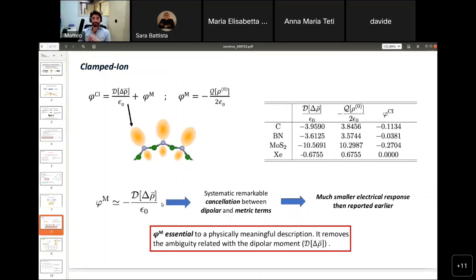We find that the Clamped-ion response, applying the prescription described before, that is, describing the quantity in the curvilinear frame of the bent layer, can be written as the sum of two contributions. One is the dipolar moment of the charge density response, precisely as seen in the moving frame of the bent layer, plus a previously overlooked term that is proportional to the quadrupolar moment of the charge density referred to the flat, initial configuration.